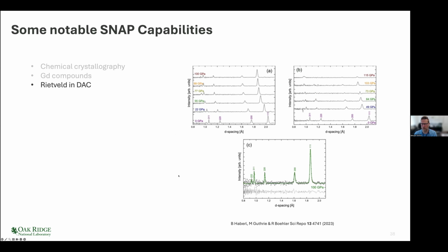And then, of course, is the work of doing Rietveld in a DAC. This is a measurement of nickel, and what you see on the bottom here is a full Rietveld refinement at 100 GPa of a sample measured in a DAC on SNAP. And this is not putting weird and wacky 10th order spherical harmonics texture parameters into the refinement. This is just the pure structure, demonstrating that the intensities coming out are meaningful. This particular paper was an example where it did take me weeks to get all these intensities properly corrected for the effects of the diamond cell. And this can be done now in minutes.